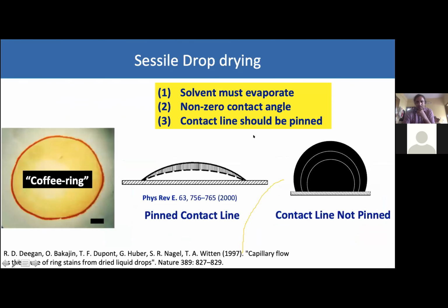Now when sessile drops are evaporating, this coffee ring that I mentioned forms only under certain conditions. That means certain conditions have to be met for the formation of such coffee ring deposits. One is that the solvent must evaporate. That means the fluid in which the particles are dispersed must evaporate, and typically drying drop experiments are conducted with aqueous dispersions, and since water evaporates under ambient conditions, the first condition is met.